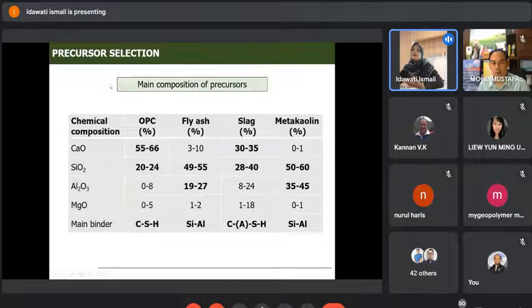If you look at the main compositions of all these precursors, normal Portland cement would have very high calcium oxide and silica oxide. These two, the calcium and silica oxide, are the ones that will contribute to the main binder, the calcium silicate hydrate, CSH.